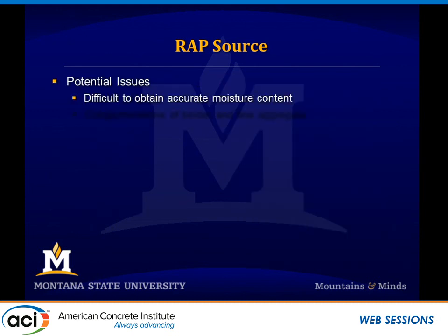We did find some issues with it, okay? When we tried to quantify the moisture content, that was very difficult, right? All of this stuff has like an asphalt coating on it, and so how you define what SSD is and what the moisture content is, and how do you heat it up to burn off or to dry it out so you can measure these things, it was really difficult, right? And so we decided that this is going to be an issue when we go on from here.